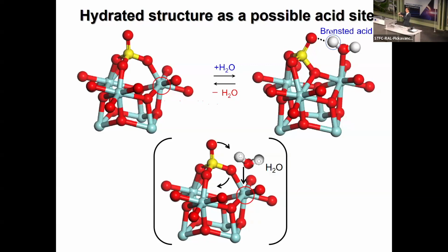Thin plate, this phase is 001. The surface area of the 001 plate is very much high compared to the conventional. And again, on the 001 surface, sulfate anions are located totally isolated. That's why the material shows such a high performance for any, not any, but many acid catalyzed reactions.